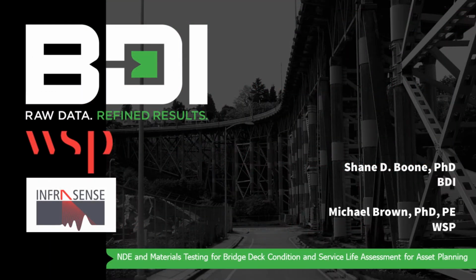How was the instrumentation able to differentiate between transverse and longitudinal, both upper and lower bars? Well, on GPR, we only capture the transverse bars because we're traveling across them. If we wanted to get the longitudinal bars, we'd have to do a scan across them. GPRs typically are only unidirectional in their antenna focusing technique. So for the high-speed work, unless we go back and do a ground-coupled system, we only get the transverse bars.